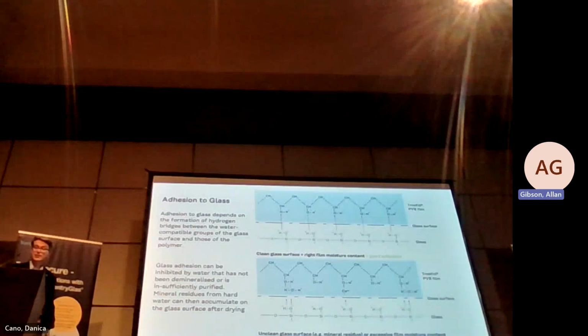And as important is the storage of the interlayer. Moisture content of the material can adversely affect the adhesion qualities. Rolls are supplied in a protective film made of aluminium and aluminium coated polyethylene, and that prevents moisture ingress whilst the roll is being stored. After use, it really should be resealed, or if the roll is opened, it should be stored in a humidity controlled environment.